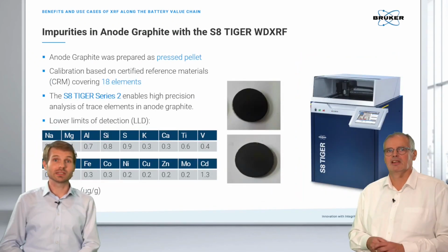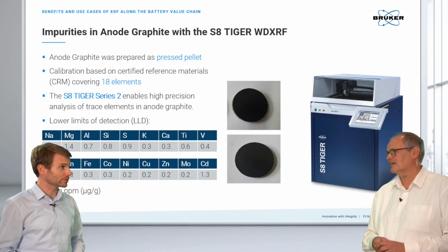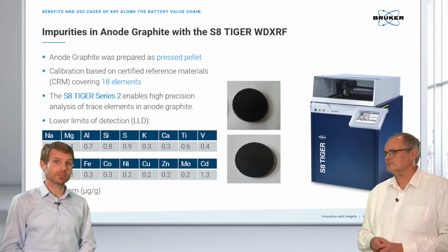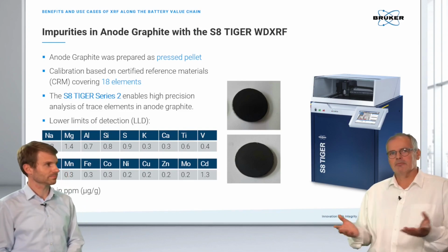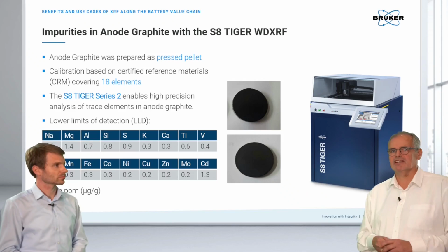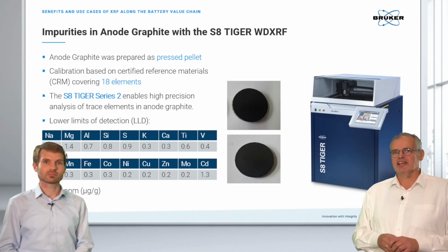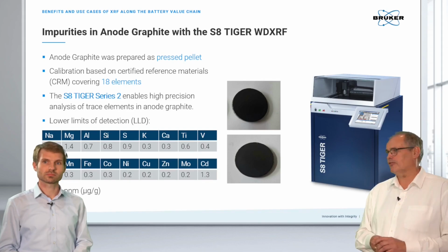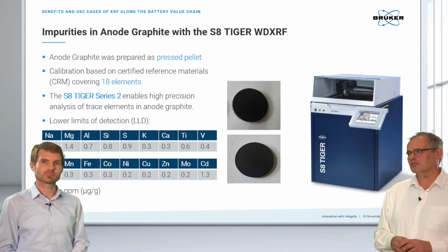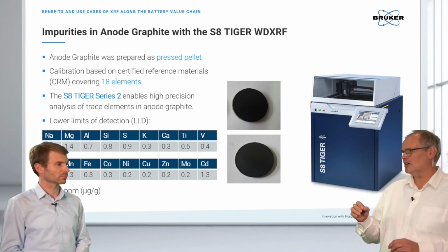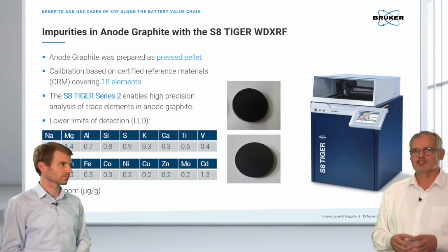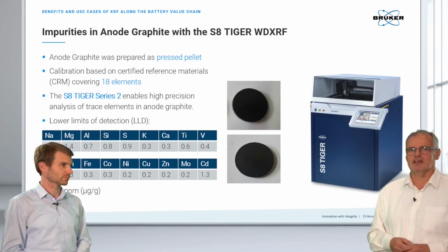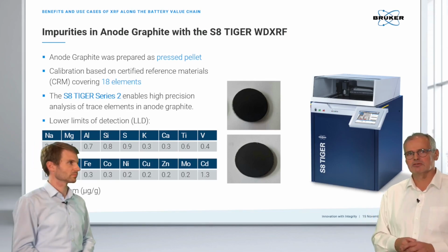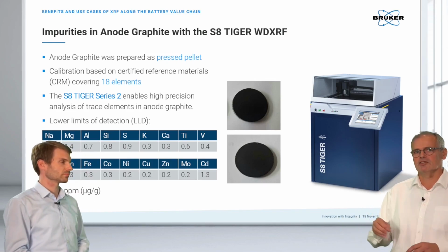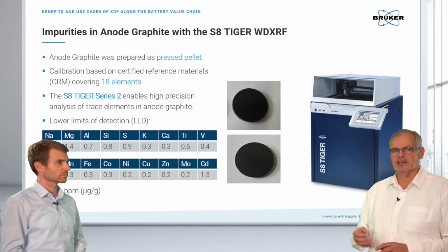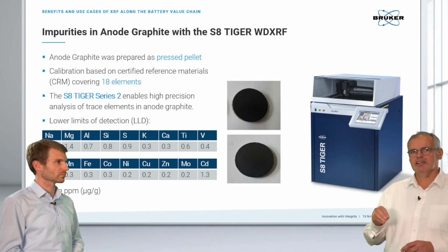Maybe a few words about anode graphite. That's one of the materials that you might receive, and this is something that you can measure quite well on the Tiger, right, Kai? Yeah, we work with 400 watt excitation power with a benchtop instrument. Nevertheless, we also have a floor-standing model which works with up to 4 kilowatts. The reason is quite simple. For graphite, we look at low 1 ppm detection limits. We want to really understand the impurities, especially elements like sulfur, chlorine, but also copper. They can have a negative influence on the anode, and therefore we need a powerful detection method.